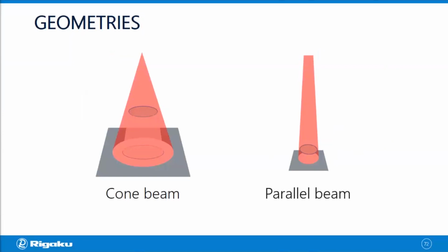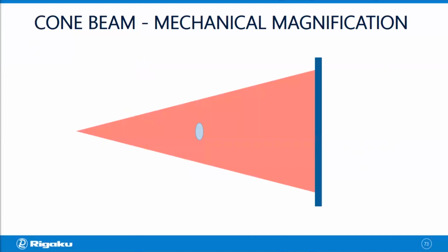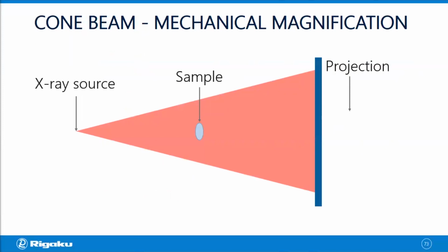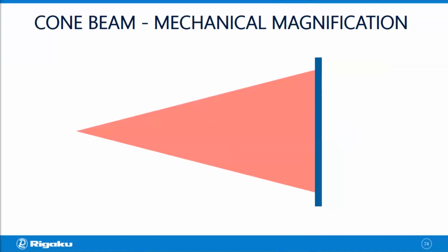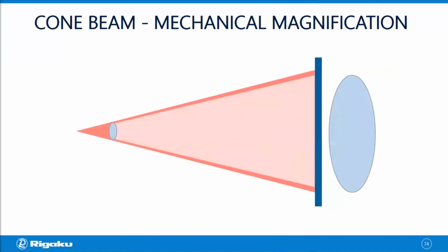For the cone beam geometry, you use mechanical magnification. So you have the X-ray source, sample, and you're gonna have the sample image projection on the detector like this. And because you have quite a bit of divergence of the X-ray beam, if you move the sample closer to the source, your projected image gets magnified. And this is how mechanical magnification works. And this geometry is very versatile and inexpensive, and that's why it's used for a lot of conventional CT scanners.